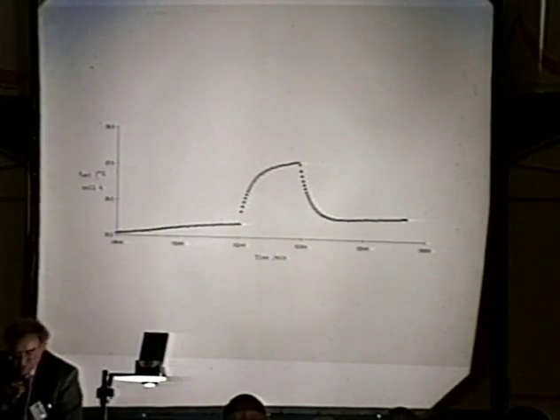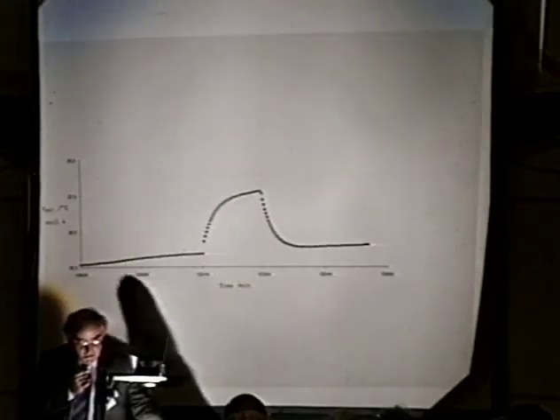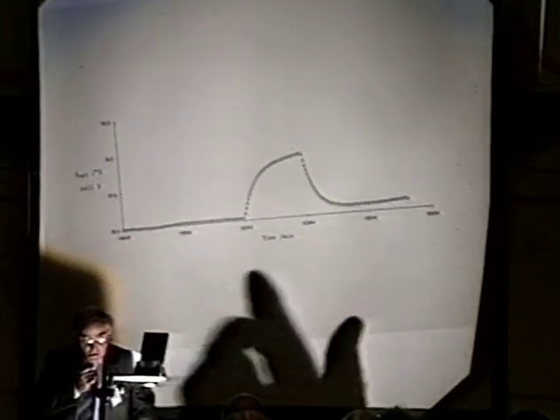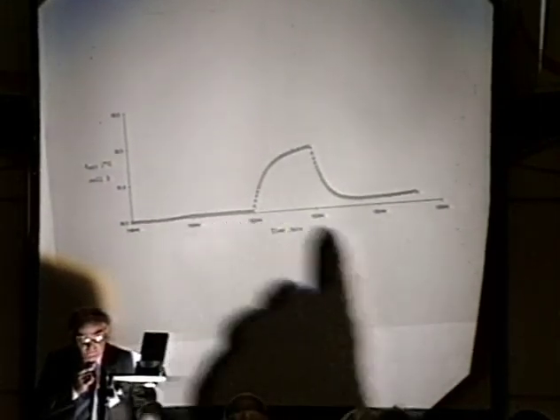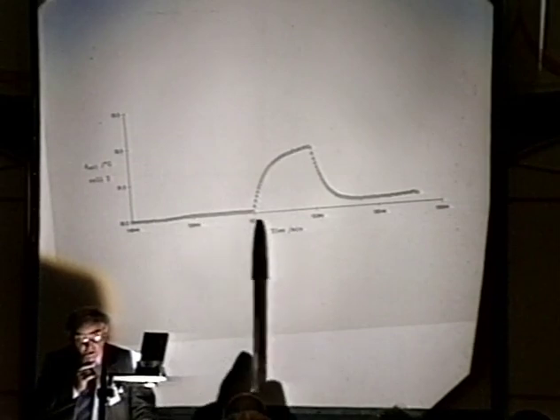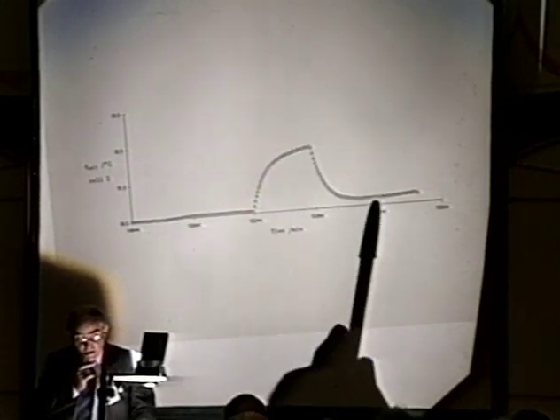And if we have the D2O cell, notice incidentally this continuation up here. We do the D2O cell, we see it doesn't relax. First of all, it's flat here. There's no change in temperature which you would expect to take place, and this doesn't relax. So you'd say, well, if there's positive feedback, if they actually managed to drive this cell into positive feedback, then they would have had a big problem in calibrating it. Well, let's reduce just that single day.